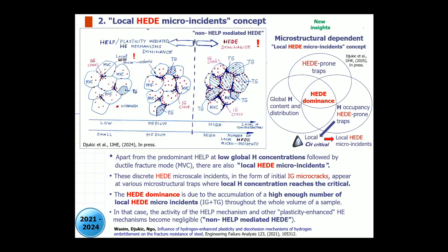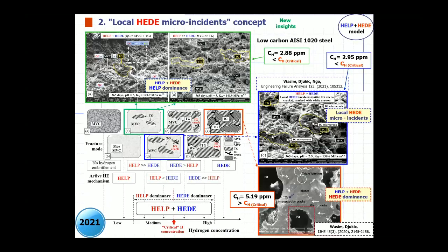With increasing hydrogen content, as you can see, we have a lot of accumulation of HEDE micro-incidents, and the concept of local micro-incidents talks about statistically when we have a large enough number of HEDE micro-incidents in the material, then we have a macroscopic drop of mechanical property and ductility of the material. So we always have ductility and brittleness in the material, but the participation of microstructural features and the activation of particular mechanisms in the microstructural location define what's going on at the microscopic level, how our material behaves. So that's still work in progress, with new insights about this concept.